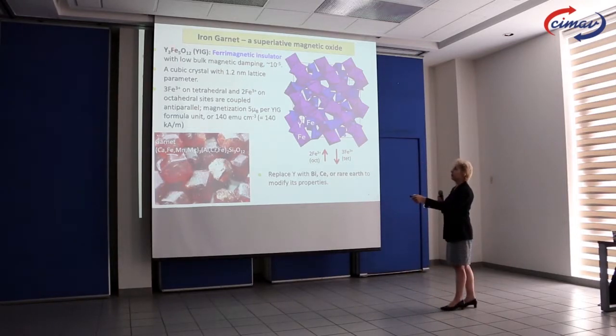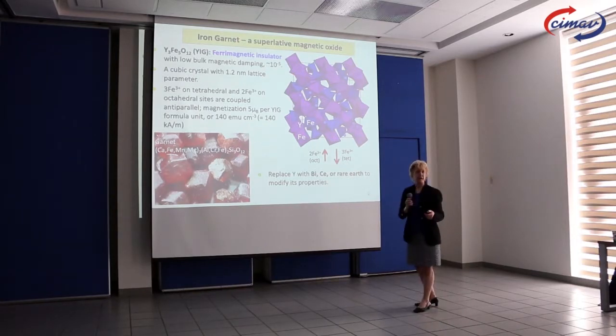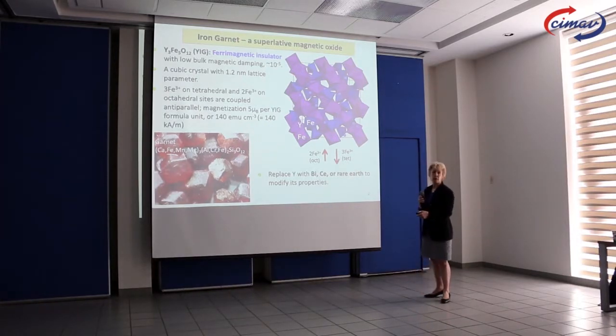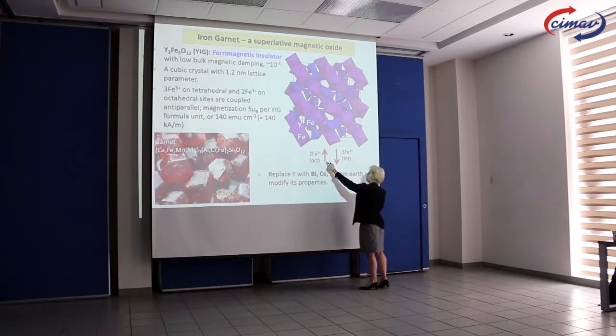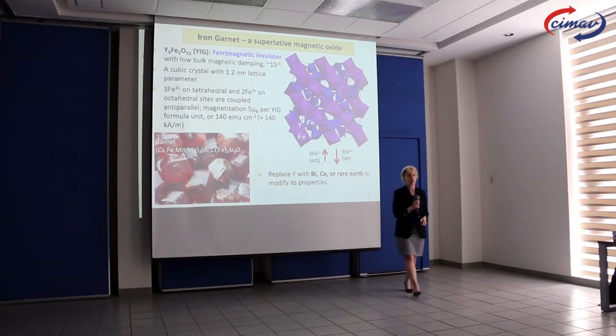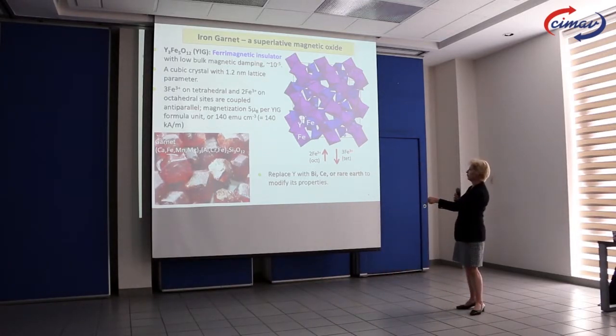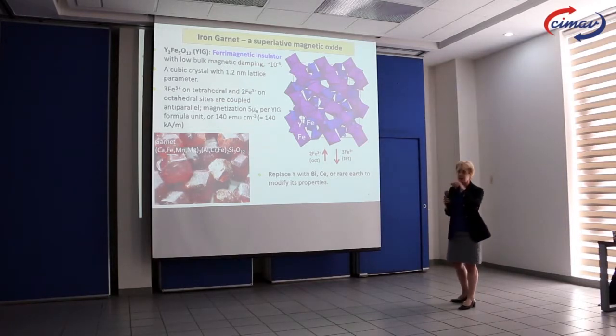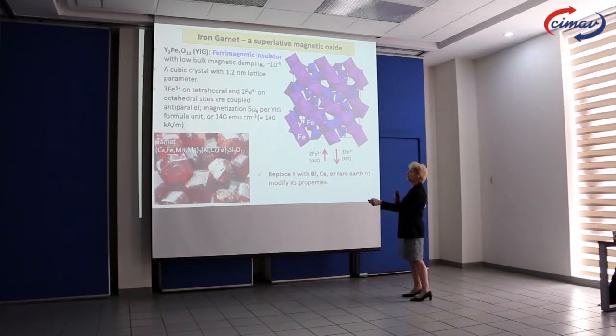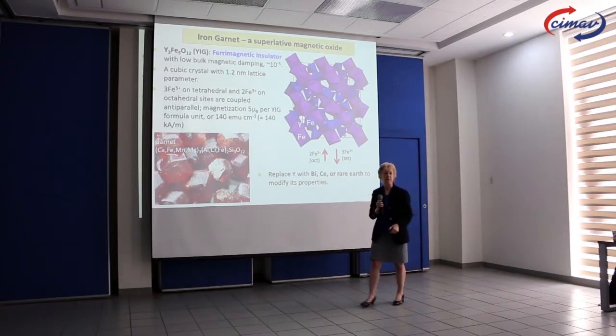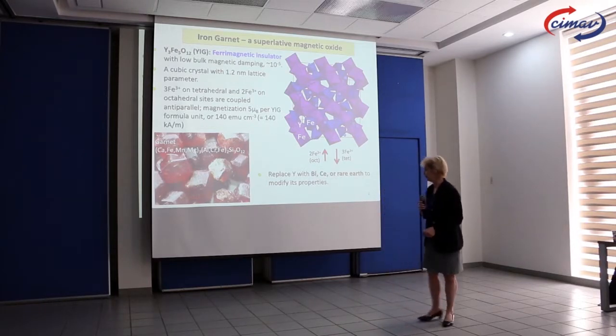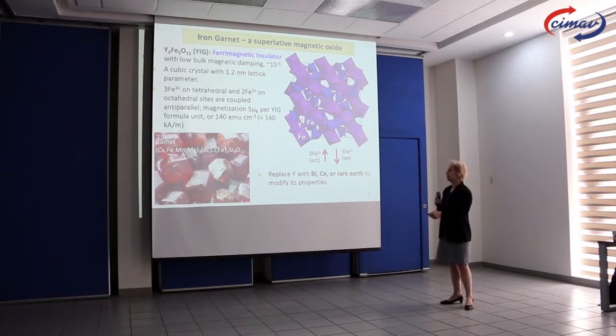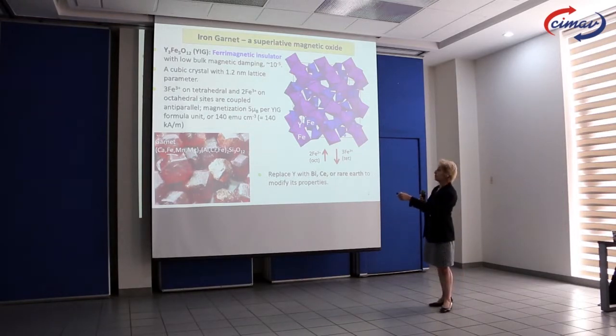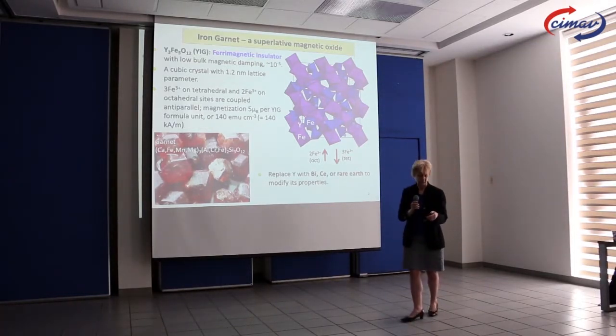And if we put iron in both sites, the iron is magnetic, and the two orientations of the iron are pointing in opposite directions. The iron in the octahedral sites points one way, and the iron in the tetrahedral sites points the other way. Because there are two of those and three of those, we have a net magnetization, which is 5 Bohr magnetons per formula unit. That comes out to 140 emu per cc, or 140 kA per meter, for the magnetization of this material. So that's what we're starting with, this YIG. It's an oxide, it's a good insulator, and it's a ferrimagnet. And its crystal structure is quite large. It has a 1.2 nanometer lattice parameter.